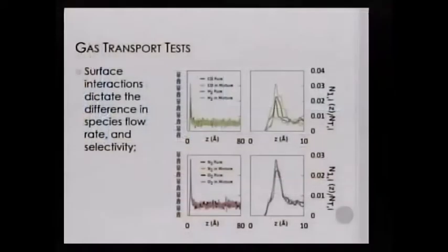And this process was not observed here, both in the mixture and in prior simulations. The profile of adsorption is quite the same. So in this case, we see that the adsorbed molecules in the membrane are actually assisting to block the larger molecule from passing, and by so doing increasing the real selectivity when compared to the ideal selectivity.